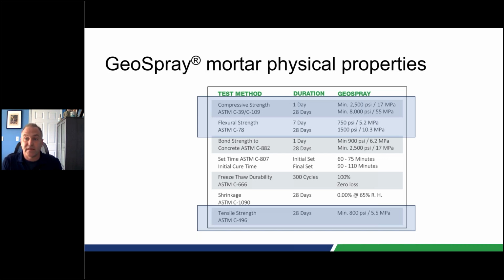When you think about cementitious materials, the general rule of thumb is that if you take the compressive strength, so in this case, the minimum values of 8,000 PSI, you would typically see a flexural strength somewhere around 1/10 that. So you would be expecting to see a flexural strength that's more like 800 PSI, and you would expect to see a tensile strength also 1/10 of that, so typically around 800 PSI. And you can see here that the tensile strength of Geospray is around 1/10, 800 PSI. That's the value at the bottom of the chart. You can see the flexural strength value is almost twice that. And that has a lot of advantages in the design properties, as well as a few other places that we will talk to when we get to that point.